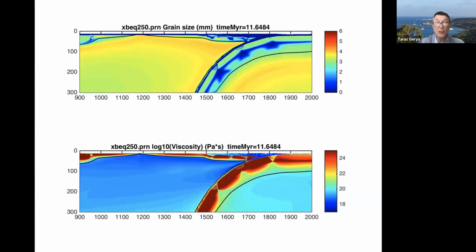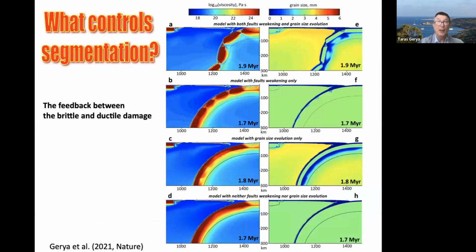So it can continue in the same manner for a very long time. So the process is self-sustained. And when we tried to find out what is the master process and what is the slave process, we performed some experiments where we were activating different weakening mechanisms. For example, this is an experiment where fault weakening, strain weakening, and grain size evolution are both present. And then we see the segmentation of the slab is well developed, and there is no doubt that this process happened here. However, if only fault weakening is introduced, this segmentation does not disappear completely, but becomes quite rudimentary.